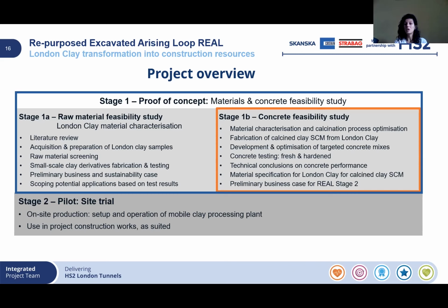is currently ongoing, which is the actual concrete feasibility study, where we essentially got bigger quantities of London clay, this time from our works, to rerun material characterization to essentially verify the prior intelligence, and therefrom fabricate bigger quantities of the London clay calcined supplementary cementitious materials, and run tests at lab scale with paste and mortars, and as currently underway, run tests with actual concrete samples, fresh and hardened,